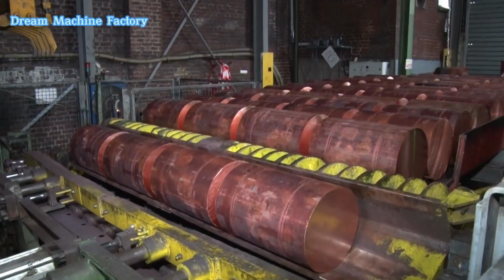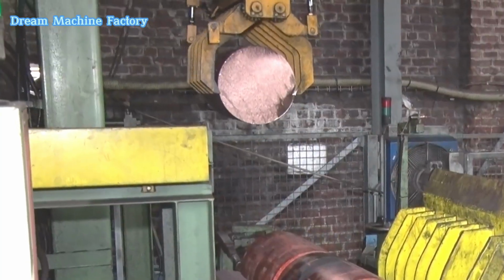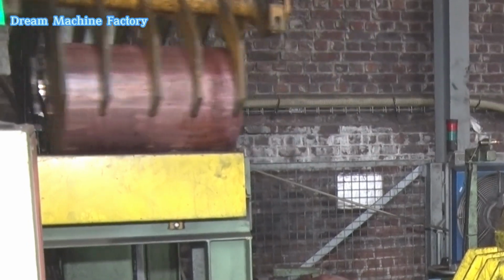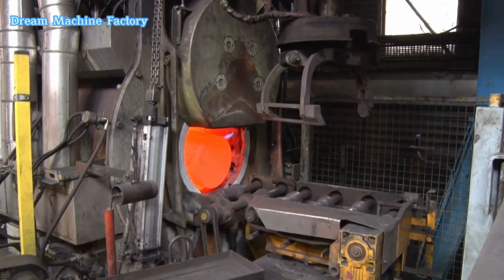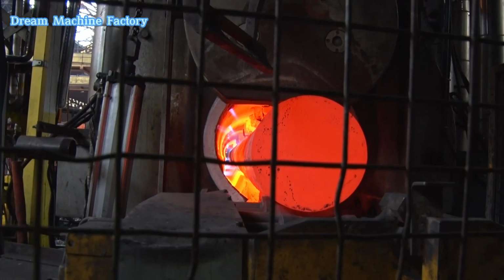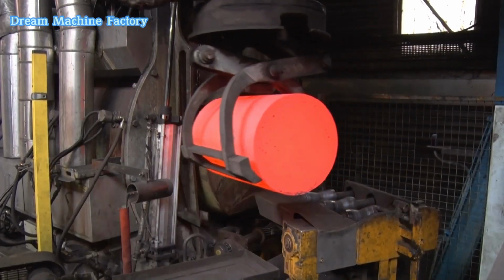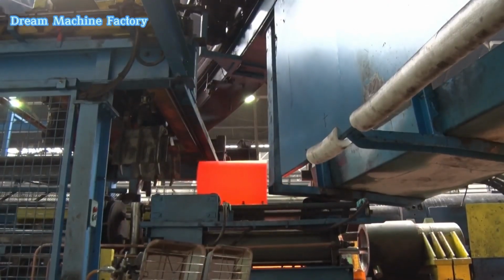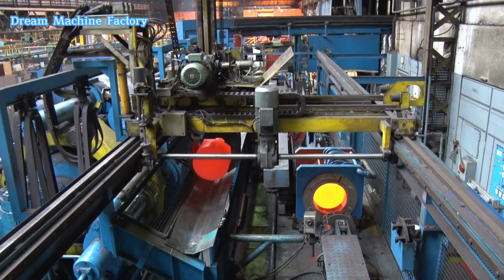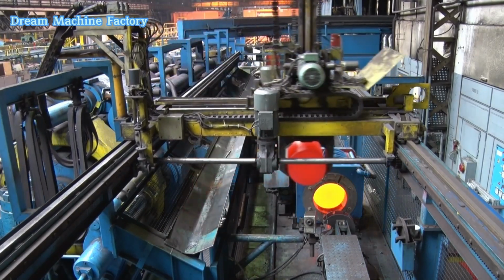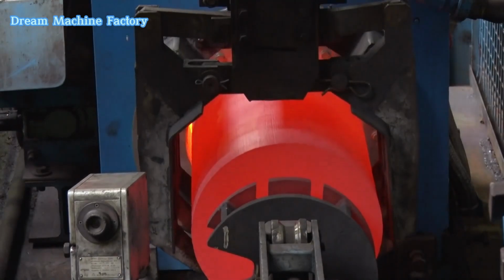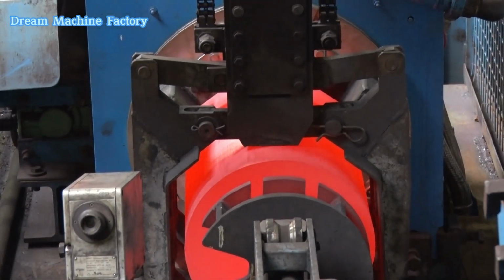long. This newly formed tube is rapidly cooled to prevent oxidation, marking the only hot-forming step in the entire process. Subsequent processes are performed at room temperature. The extruded tube undergoes cold rolling, where it is passed through conical grooved dies and over a mandrel to reduce its diameter and wall thickness.